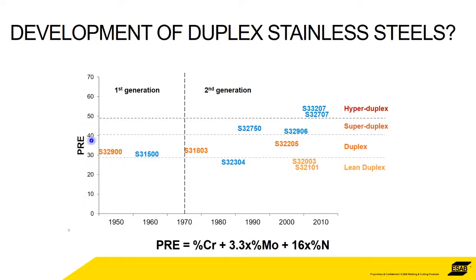Up the y-axis is this thing called the PRE, the pitting resistance equivalent number. So this is the equation for it. It's got no units, it just comes out with a number, and it's an addition of the percentage of chrome, molybdenum, and nitrogen within the alloy. Add that up, and you come out with a number. The definition of the duplex family is made by using the PRE number.